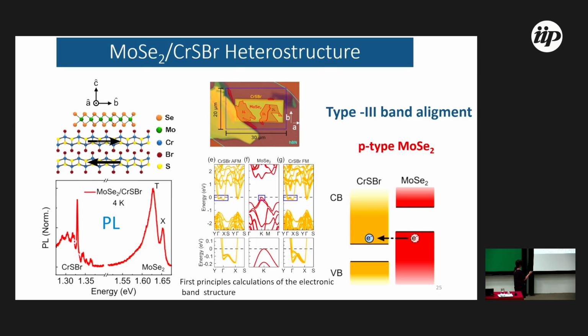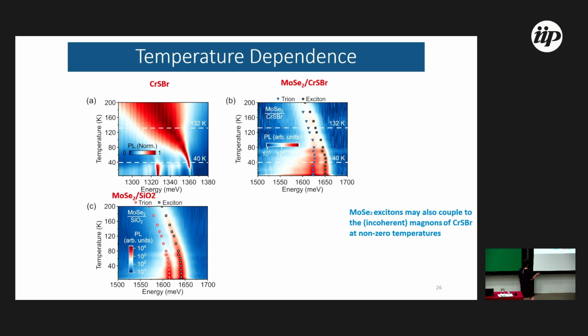And so just the calculation that they perform to show that it's type 3, that the charge transfer is very efficient. And also because we changed the doping. Usually MoSe2 is N-type, but due to this charge transfer it is P-type doping because of this band alignment. So what happens? The first thing here is about magnons.